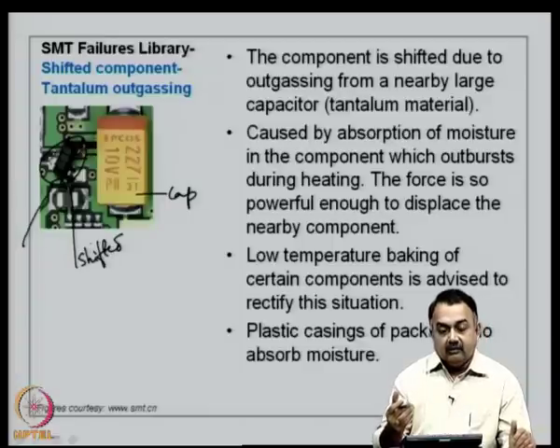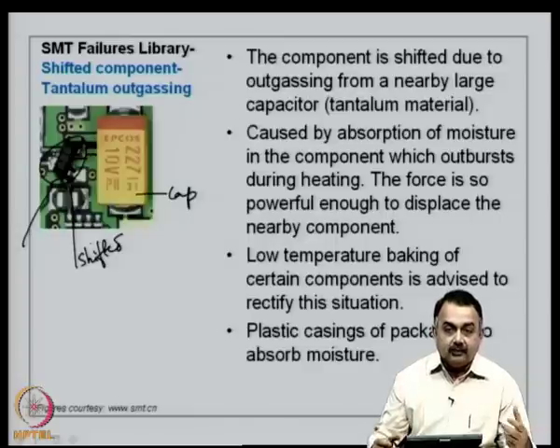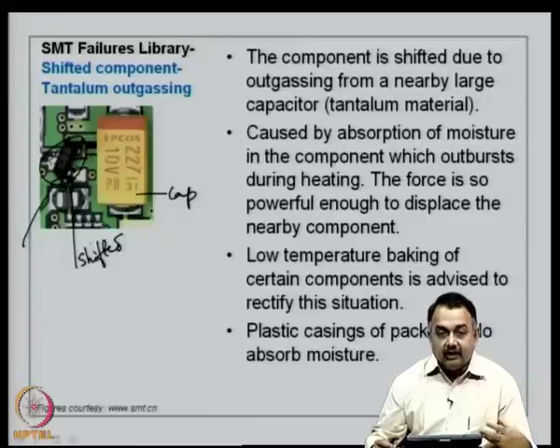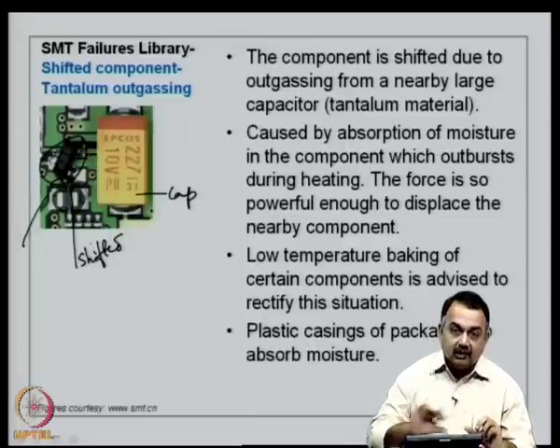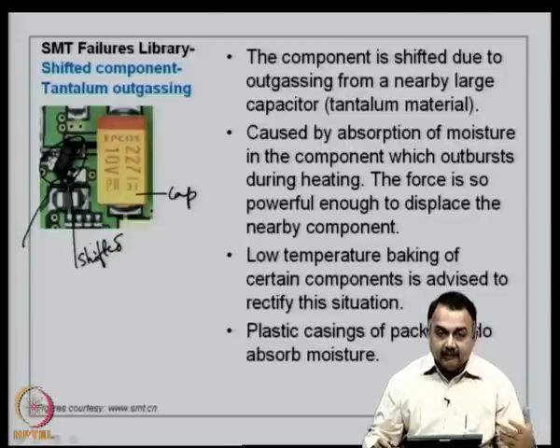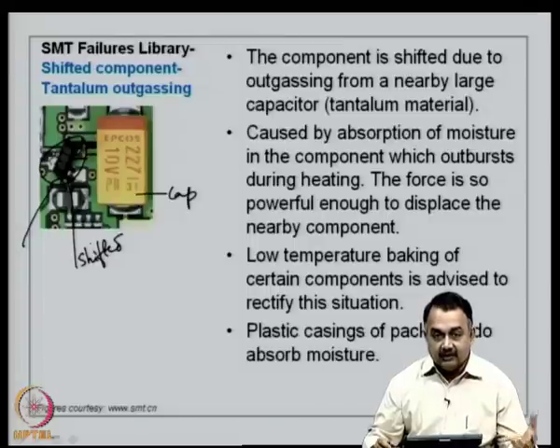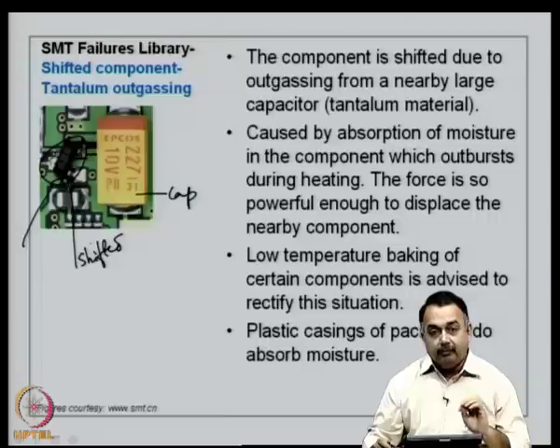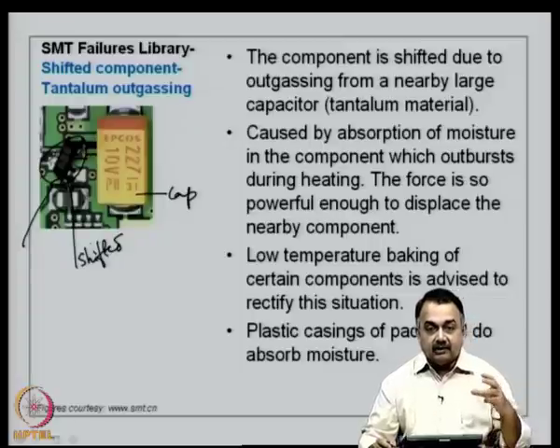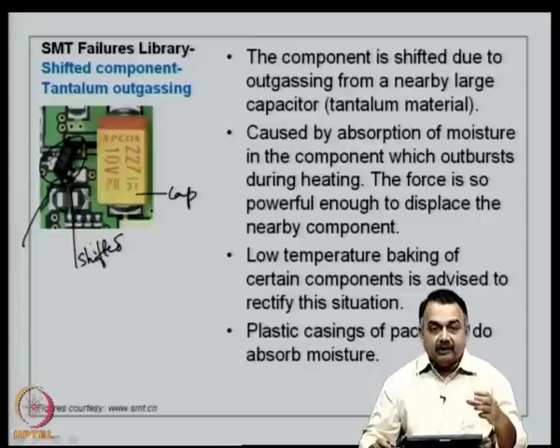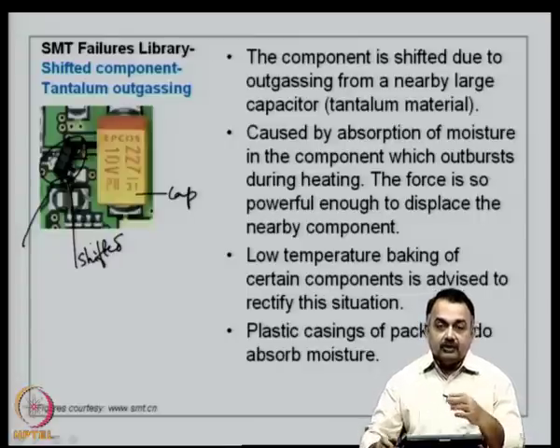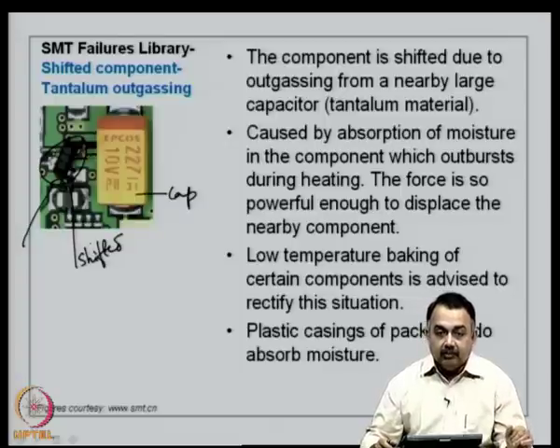The reason is simple. The capacitor has absorbed moisture during its storage period. Now, what you have done is you have directly used the component without doing a preheating, and then during the heating of the soldering process, the water is being removed from the component. There is an outburst of gases, there is outgassing, and this is so powerful that it displaces the nearby small component. How does it displace? Because the small component is actually swimming in the solder paste during the reflow process before it is cooled.